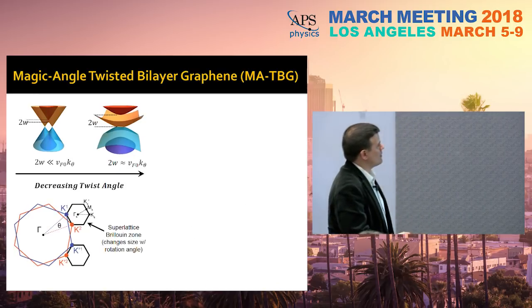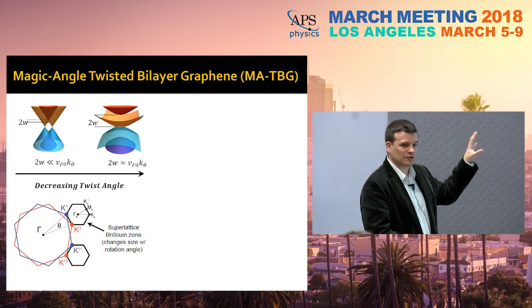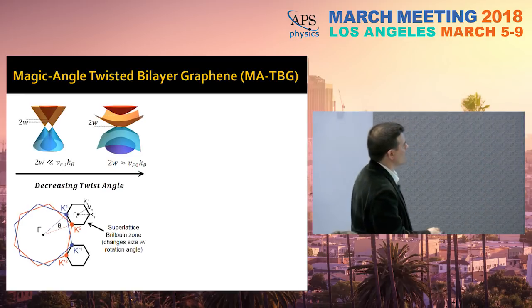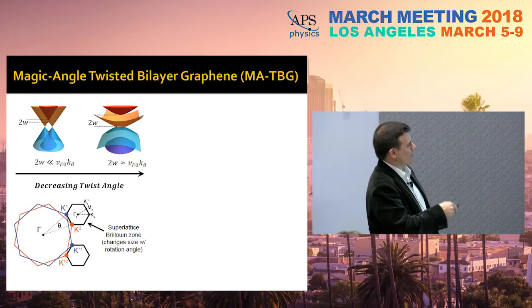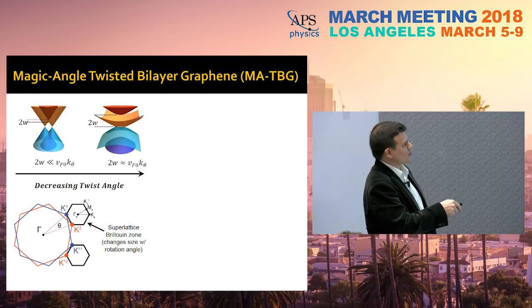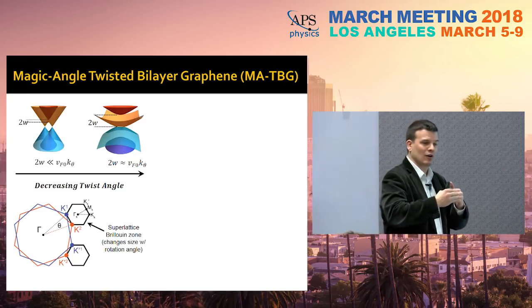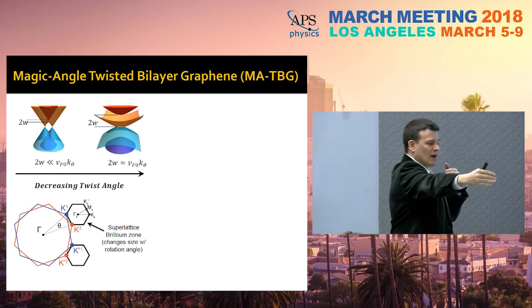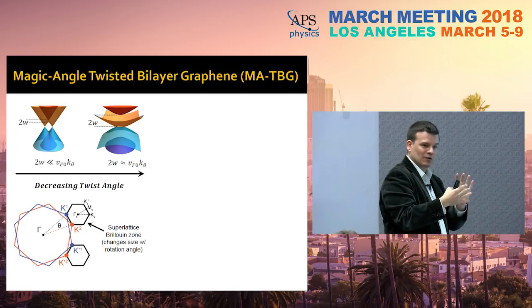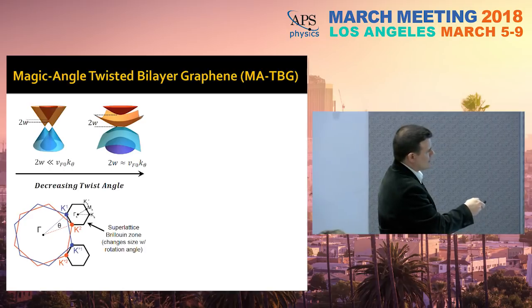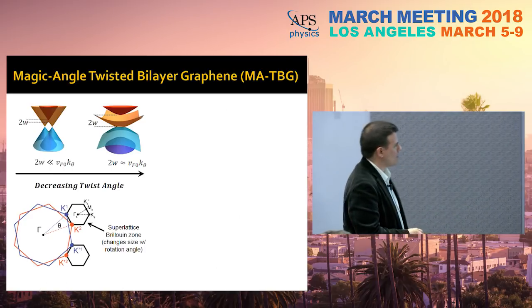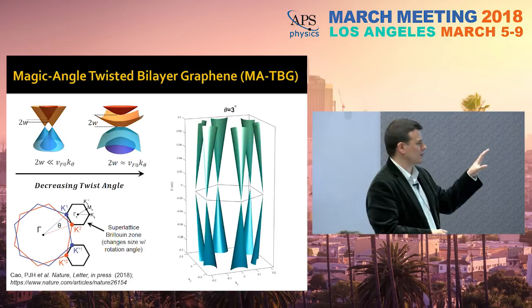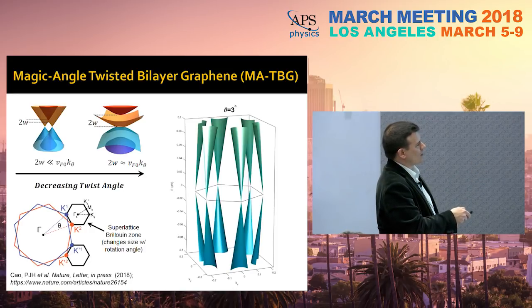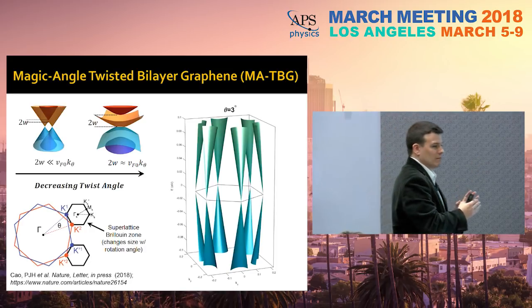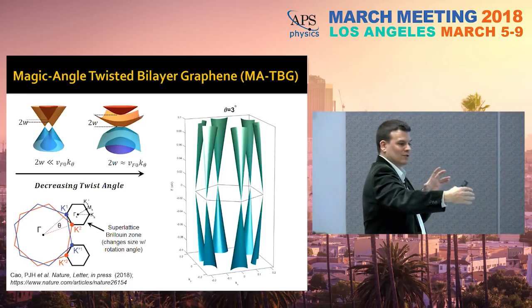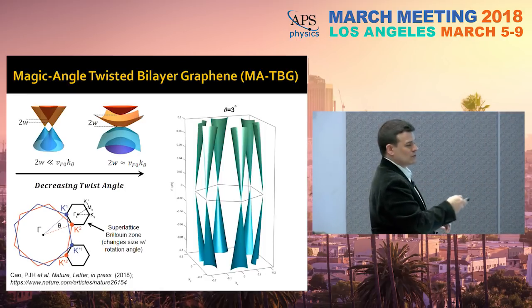So let me tell you now what happens in the evolution of the electronic structure as you are doing this process. Here I'm showing the two reciprocal space lattices. This is the superlattice Brillouin zone. Because you have a long wavelength moiré pattern, you have a smaller superlattice Brillouin zone. In momentum space, you are small. It's this little hexagon here. I'm going to show now a video of the evolution of the band structure. As I rotate towards smaller angle, the moiré wavelength becomes larger, so the superlattice Brillouin zone becomes smaller, and you're going to see what happens to the electronic structure.